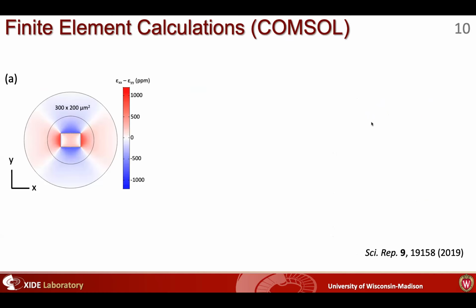So to probe this a little bit more, we did finite element method calculations using COMSOL. And what we found was, again, just to skip some of the details, if we plot the differential in-plane strain, it agrees that the more compressive direction would be along the short axis of the electrode. So this is x minus y, meaning that positive x is more tensile, y is more compressive.